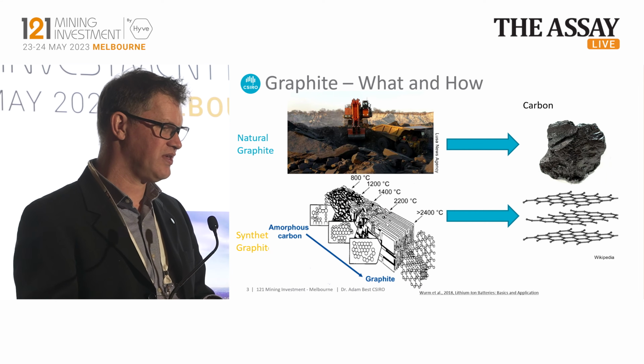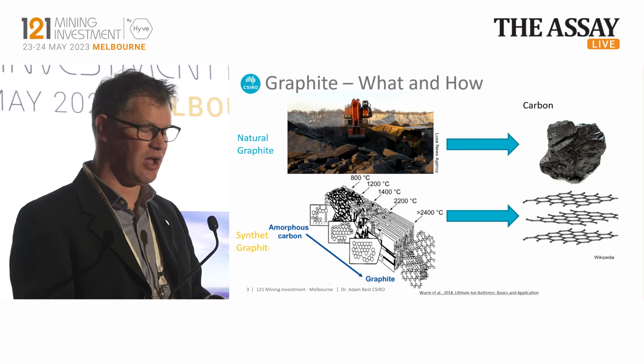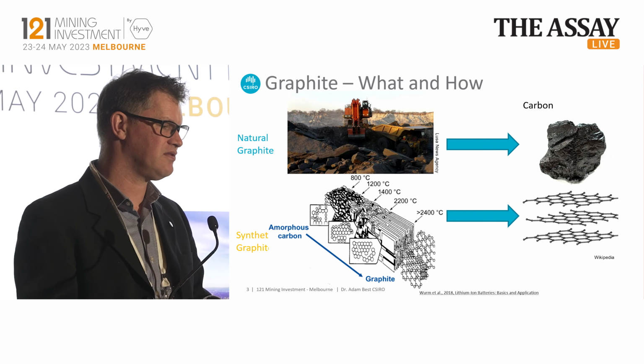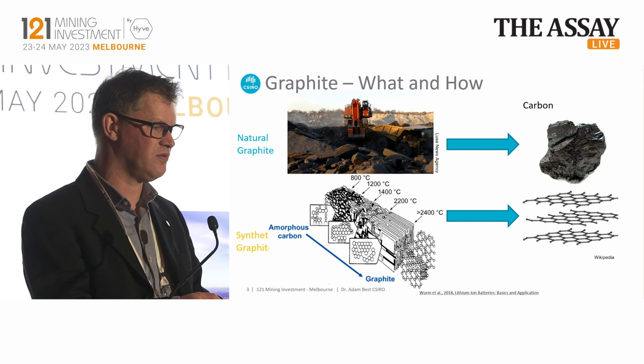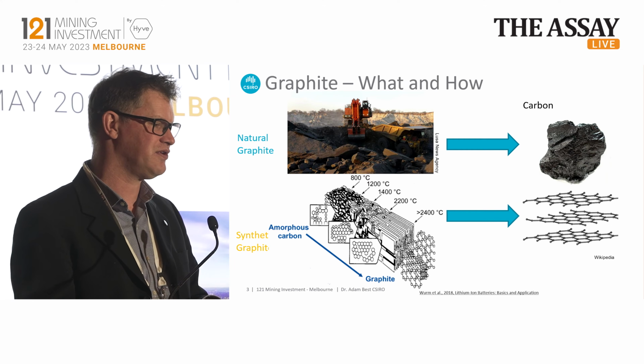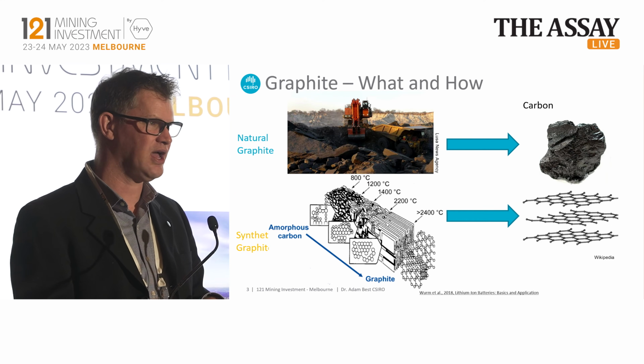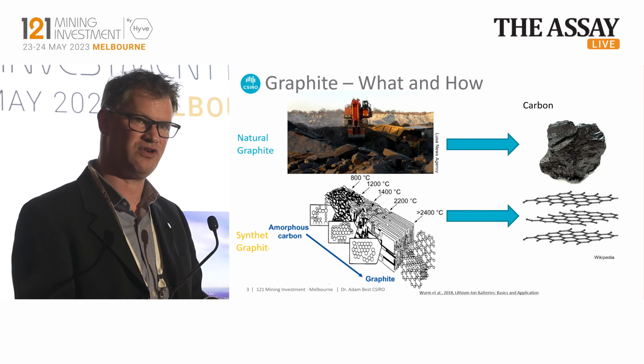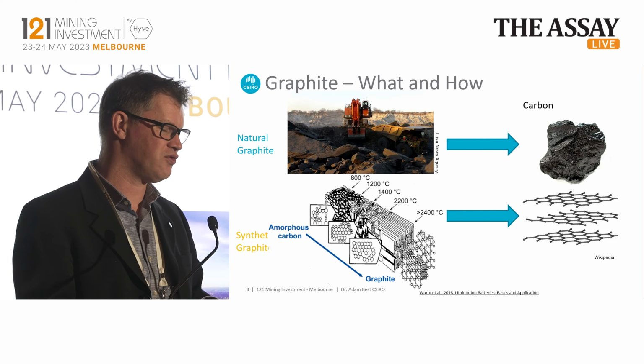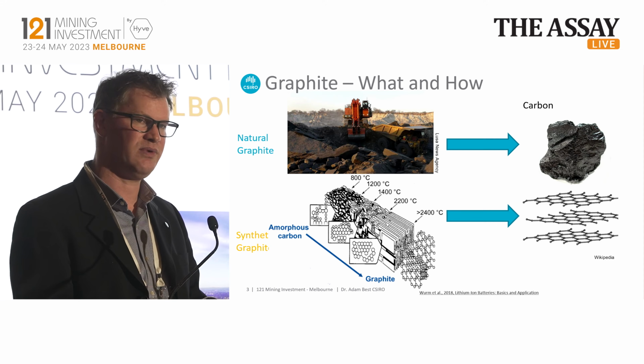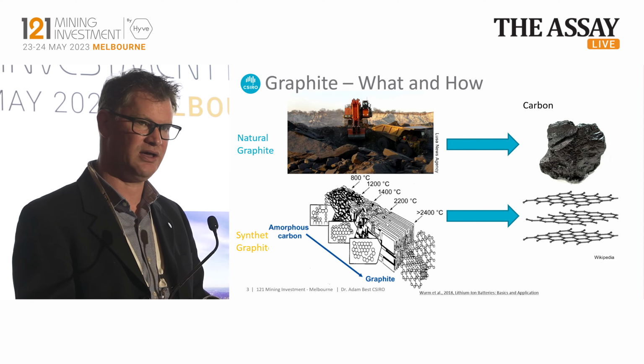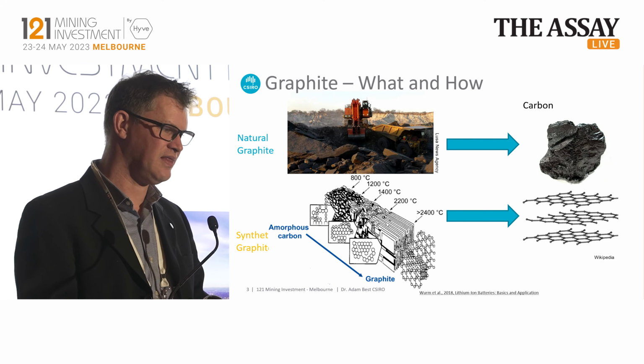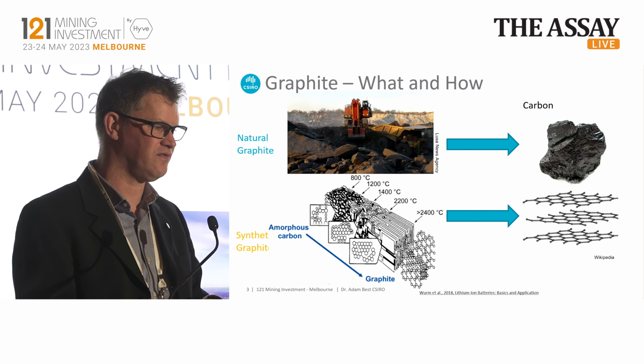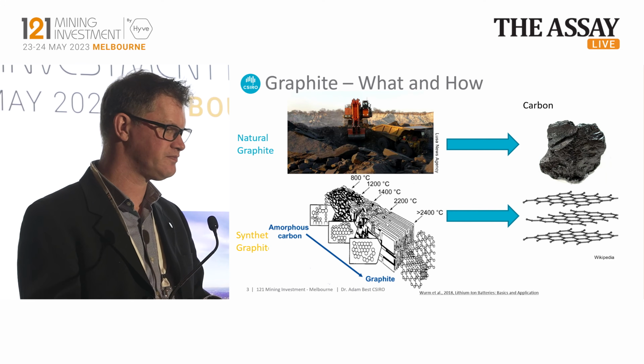So when we think about graphite in Australia, and in terms of natural graphite, here's the type of things that we're looking for. As you go from amorphous carbon at lower temperatures, this is what has very good ionic conductivity and electrical conductivity, and this is what's used to coat graphite. And through to, as you go higher and higher in temperature, we see more of this lattice ordering until we get to the graphitic material that we use inside a battery. And that graphitic ordered material is what's needed for battery materials.